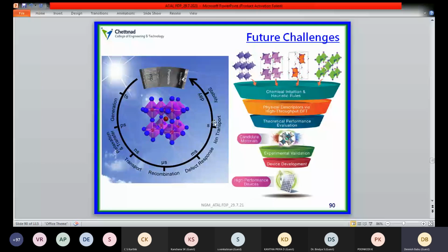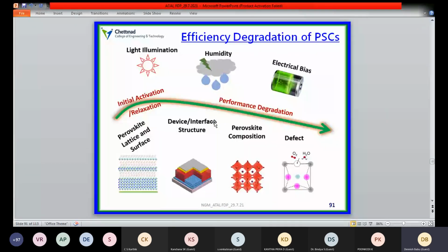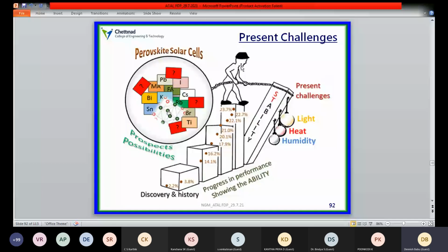Especially the light illumination, humidity, electrical bias, and perovskite composition defects. There are many efficiency degradation parameters available, so if you overcome this degradation, it will lead to a good power conversion efficiency from perovskite solar cells. Yes, these are the present challenges in the PSC: light, heat, and humidity, which are degrading the performance of these perovskite solar cells at industrial scale.